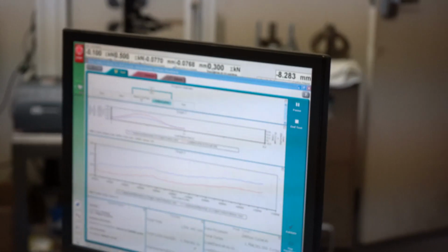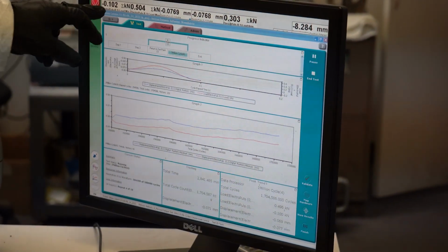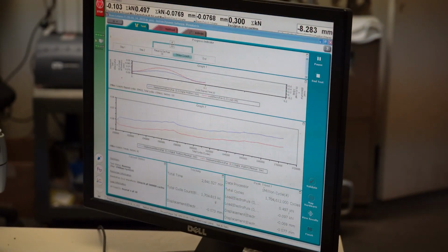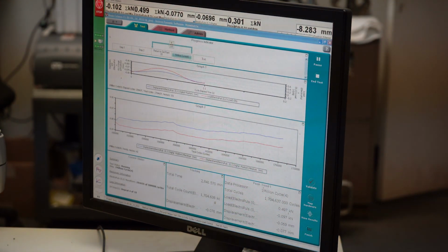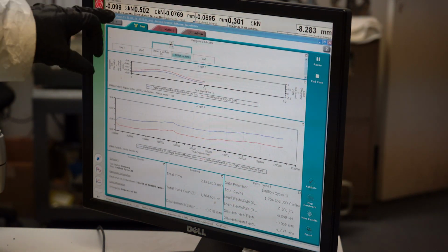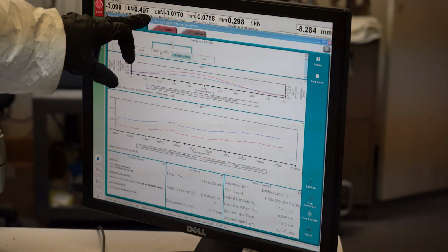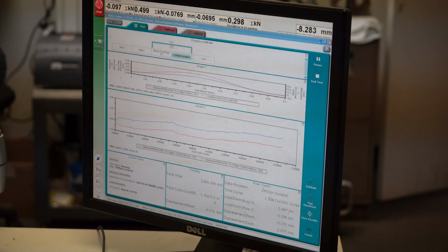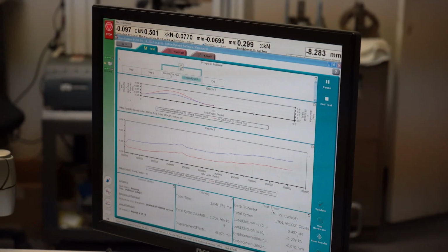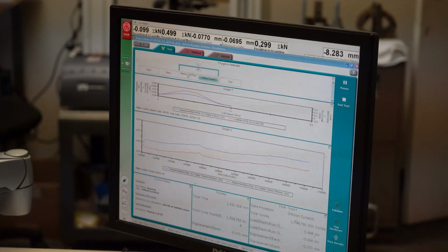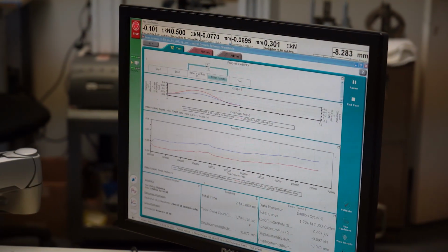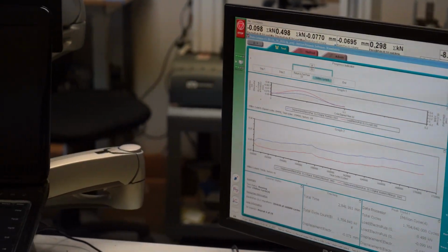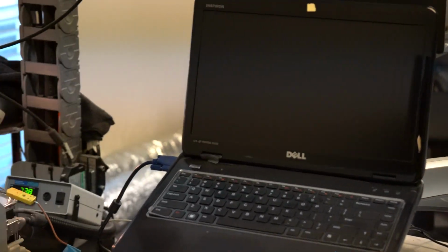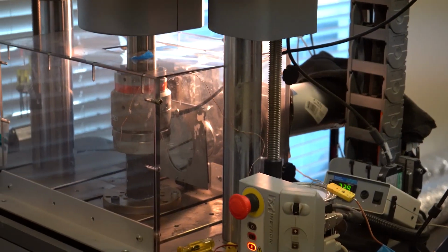As you can see from the screen, it's at 10 Hertz, which means it's 10 times up and down per second, and it gives 0.5 kilonewton load for tensile and minus 0.1 kilonewton load for compression in a 10 times per second cyclic load. The temperature inside this chamber is about 74 Fahrenheit, at room temperature.